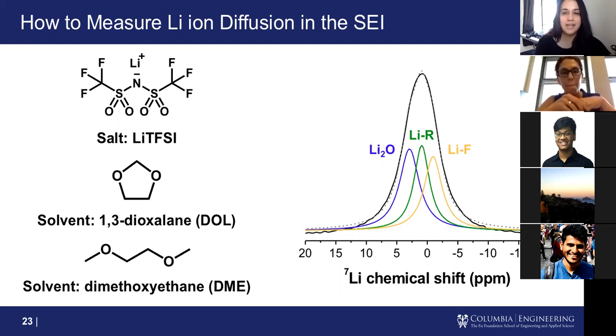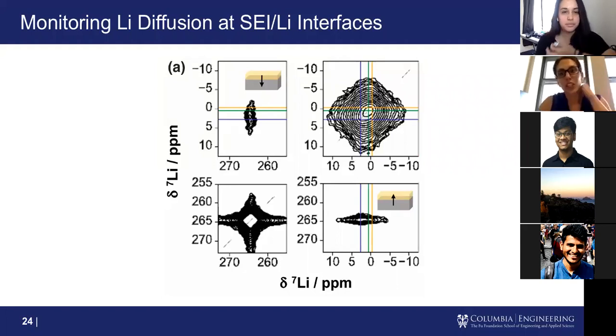Okay, and then on the next slide, it says, what's the name of the spectroscopy used? This is called exchange spectroscopy. Okay, and then another question says, has simulation been able to replicate the behavior observed in your experiment? We have not. If you're referring to the deposition itself, we haven't done any mesoscale modeling of the deposition behavior. We have done density functional theory calculations looking at the electrolyte decomposition at the lithium electrolyte interface, and they do match the trends that we see in SEI formation and electrolyte decomposition with NMR.